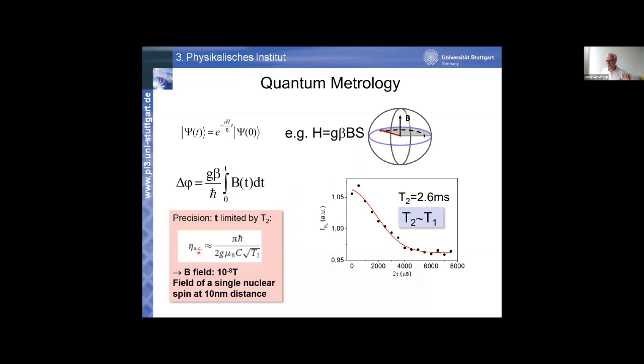But maybe I'm commenting a bit on this equation here. Essentially, the sensitivity is limited by T2. So T2, the dephasing time, goes in as the square root of T2 as long as we are scaling with the standard quantum limit. The other parameters here are rather constant, except the C. The C is the contrast, so that's the signal amplitude. What people typically fight with in these experiments is getting the contrast, the signal, as large as possible, and getting this T2, the averaging time, the coherent evolution time, as long as it gets.